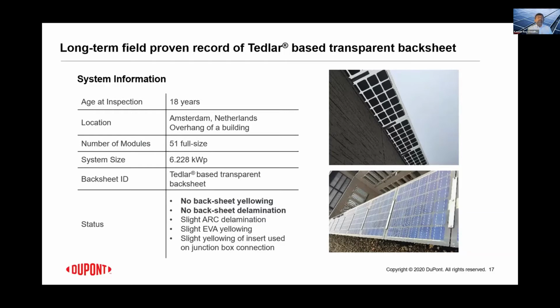This is one of the examples of those. This is in Netherlands. This is over 20 years now. It's a building integrated installation. And what it showed us was the earlier generation of Tedlar-based backsheet was actually holding up pretty well in the field, with no obvious defects that are associated with backsheets in general: no yellowing, no delamination, no cracking. And these are still operating in the field.